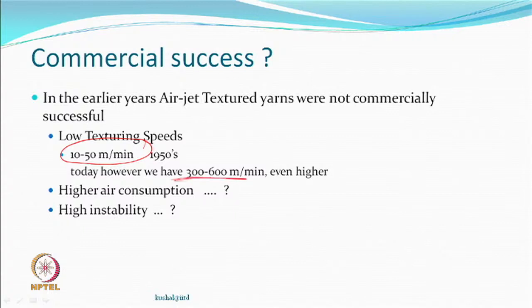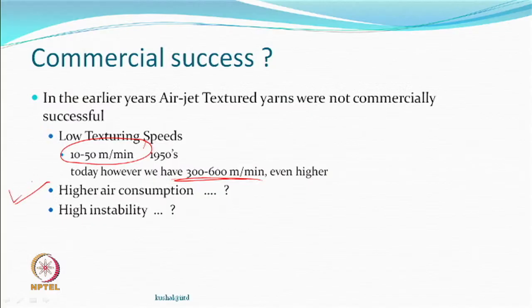After people understood what this whole process involves, they have been able to see speeds rising from 300 to 600 and even more meters per minute. But compressed air is not free — you have to work hard to compress it. If the effect is not good enough, it increases cost; or you reduce the speed so the effect is good enough.